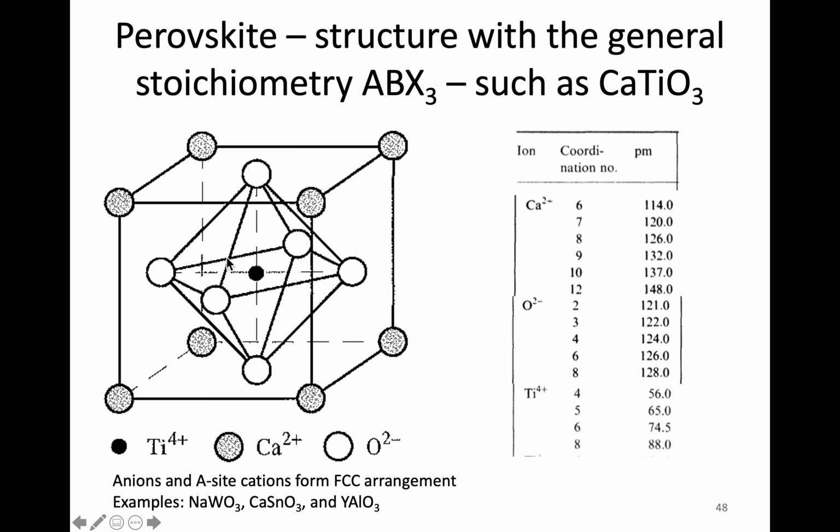And so, if each of these, the black one here, the white one, and the grayish one, if each one of those corresponds to one of the ions up here, you can imagine that the oxygen one is the one that's going to be most prevalent in the unit cell. And so that would be the white, because each one of these is counted as half. So 1/2, 1/2, 1/2, 1/2, 1/2, 1/2, and that would get us to 6 halves, so that's 3, right? So that's oxygen. Oxygen's pretty easy to count.